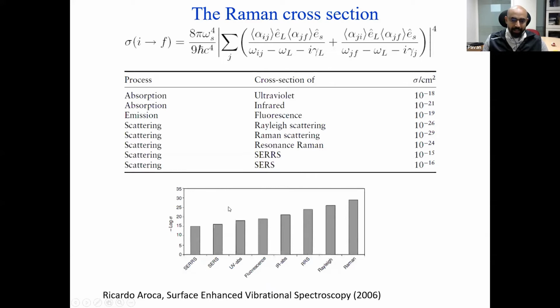Now, what is of very high interest for this particular talk is that the scattering cross sections related to surface enhanced Raman scattering and surface enhanced resonant Raman scattering can be much more than even the conventional optical processes. Now, this is the reason why SERS and other optical processes have gained so much attention, because you are now able to detect molecules beyond their conventional cross sections of detection limit, which creates a very new opportunity, and also creates some interesting problems in this particular field.